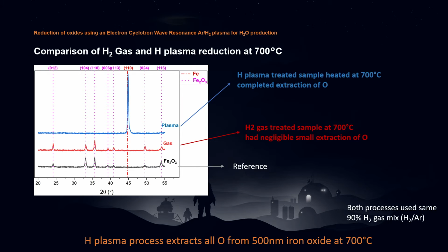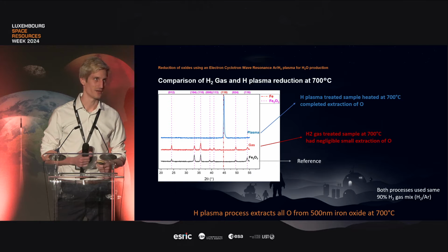We wanted to compare the processes as well, hydrogen gas and plasma process at the same temperature. In this case, we see that the red line and the black line spectrum look basically the same. It is not visible on this graph because they are stacked, but there is some extraction of oxygen occurring, but we cannot see any phase transformation. But if we look at the hydrogen plasma treated sample, which is the blue line spectrum, we see only one peak, and that peak belongs to metallic iron.